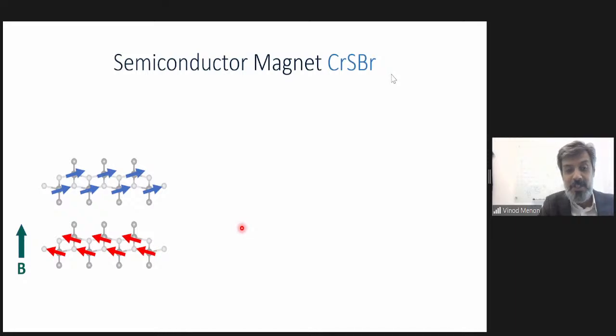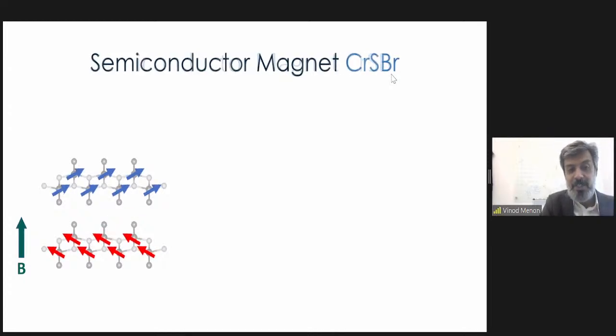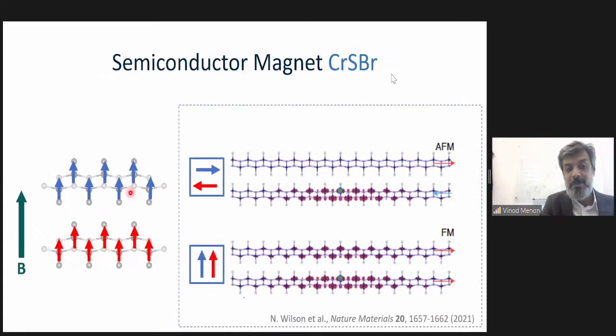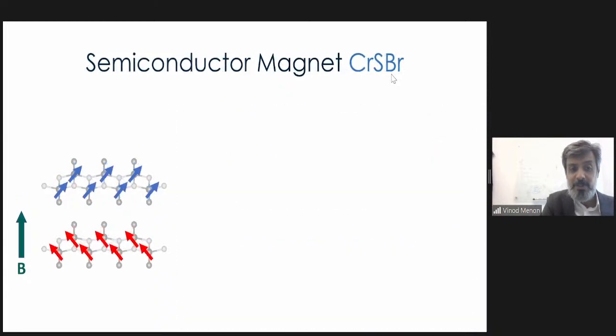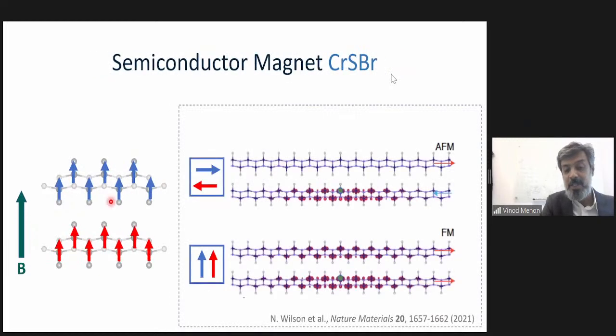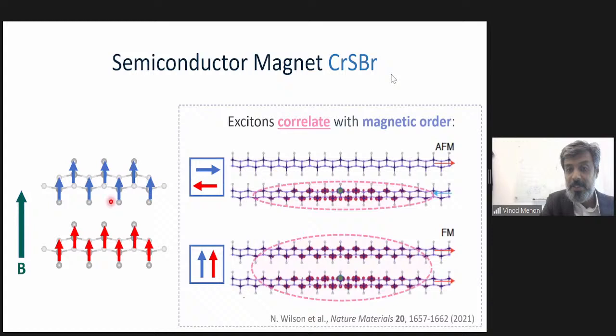So if you apply a magnetic field, all the spins in one layer start aligning, trying to rotate. These guys also start rotating. I increase the field, and then eventually at some large field, everything becomes pointing in the same direction, and you reach the saturation field where everything becomes ferromagnetic. So again, just to give an idea, you start with something which is ferromagnetic in the layer, anti-ferromagnetic between the layers. You start increasing the field, and you slowly reach this regime where everything is pointing in the same direction, or you become a ferromagnetic material.